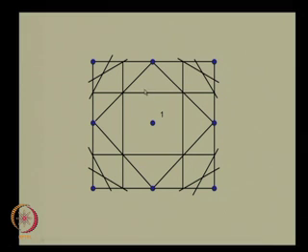If you cross one Bragg plane, but you do not cross a second Bragg plane, then that region is a second Brillouin zone. We find around this point several locations where this is true. So, this is one region where this is true, you have crossed one Bragg plane to get into this region, but you have not crossed further Bragg planes, right, and all these perpendicular bisectors are the Bragg planes by the definition that we have given them. So, we crossed one Bragg plane, we did not cross the second Bragg plane. So, this belongs to the second Brillouin zone, but there is another region here which also belongs to the second Brillouin zone for exactly the same definition, because it fits the same definition. This is another such region and this is another such region. So, taken together we have 4 locations where we identify the second Brillouin zone. So, those are the second Brillouin zone.